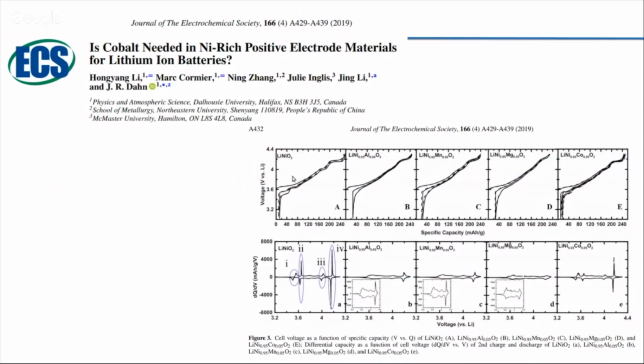For example, what you see is the testing of a battery that has 100% nickel oxide, lithium nickel oxide, as the cathode. And then they have 95% nickel, 5% aluminum; 95% nickel, 5% manganese; 95% nickel, 5% magnesium; and finally 95% nickel, 5% cobalt. And they concluded that cobalt plays a very minor role and you can neglect the role of it. So people are engineering chemistries without cobalt and it is okay. And you can still get pretty good cycle life and energy density.